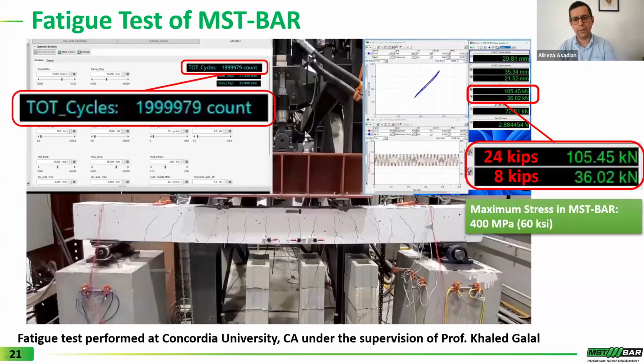Another long-term effect on GFRP reinforced concrete elements is the effect of fatigue under repeated loading. That is important, for example, for bridges or any other elements that are subjected to fatigue loading. Again, we have done some fatigue tests at Concordia University under the supervision of Professor Khaled Galal. So I have a video showing the last few cycles of one of the tests. And in this beam, maximum stress in MST bar was around 400 MPa, meaning around 60 ksi, and the